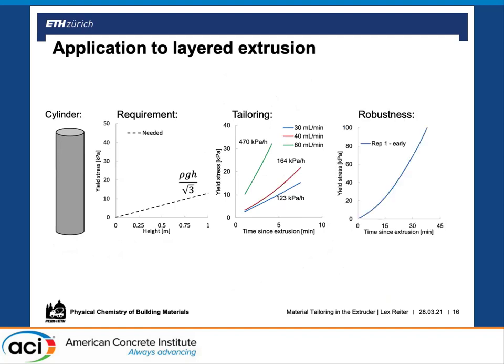We can also measure how robust this acceleration is. So we can measure once before the printing is started, once afterwards, and once on the second workday, and we get a very robust and reliable acceleration that doesn't change on a daily basis. So this is nice.